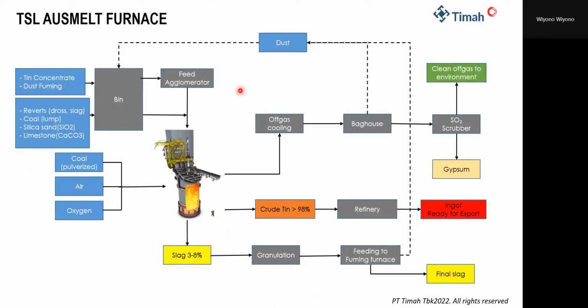So the capacity of our Ausmelt furnace equals 5 reverberatory furnaces. And the process of tin smelting, either the first stage or the second stage of tin smelting, happens continuously here. Firstly, a reduction process to get the crude tin. The first is the smelting process, and then the reduction process. After we get the crude tin, the slag from the Ausmelt is around 3 until 8%.